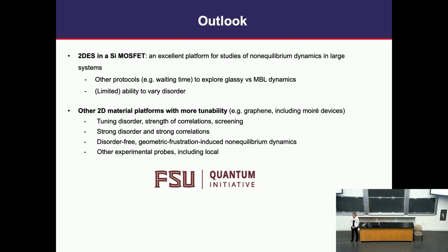Well, this was done in spin glasses. People measured AC susceptibility in spin glasses, and the fluctuation dissipation theorem is violated. It is violated, but if the system is not very far from equilibrium, it was the theoretical prediction confirmed experimentally that FDT can hold, but instead of temperature, now you have an effective temperature. But in MBL it's maybe very different. Well, yeah, this is very different, I don't think that's applicable. Here you just need to be in one many-body state.